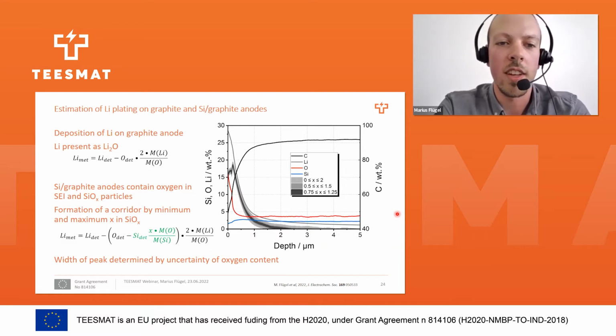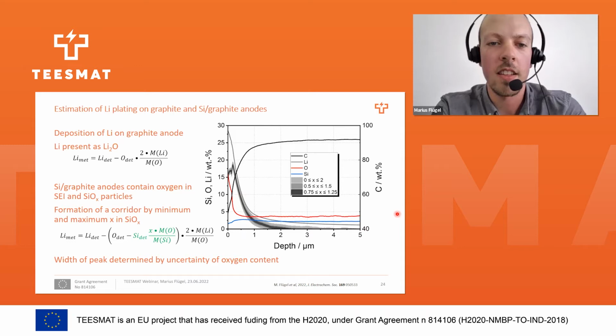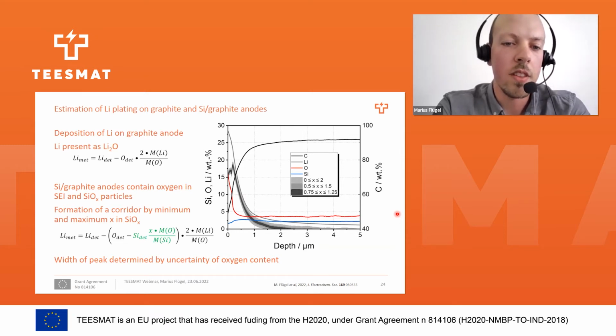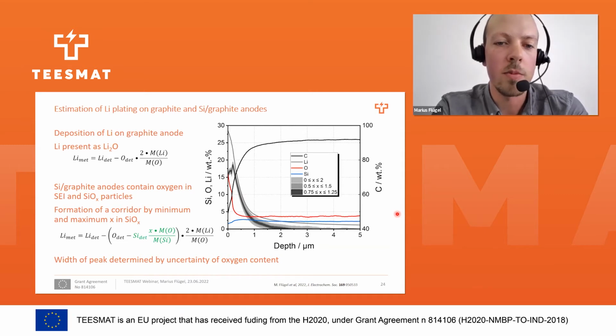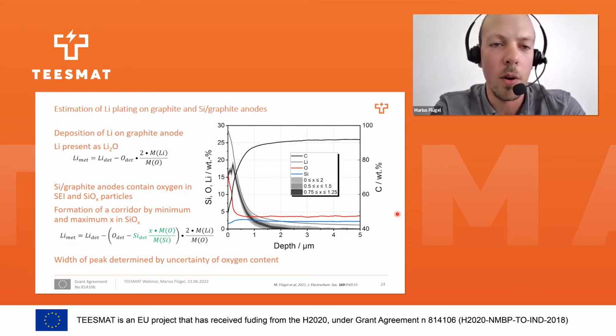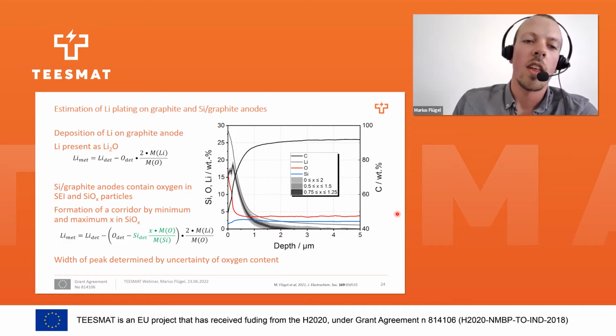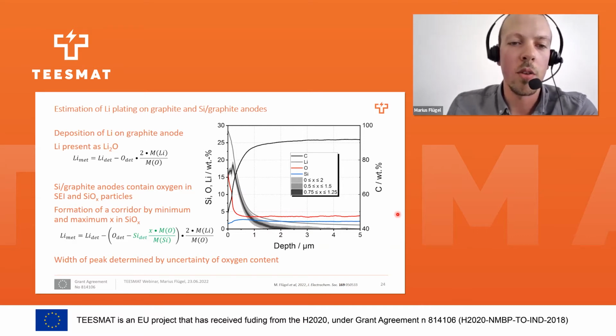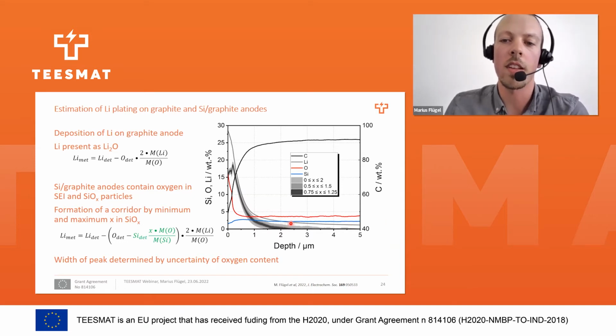For silicon-containing cells, this assumption is not so easy because silicon oxide also contains oxygen, and we have to subtract the amount of oxygen bound in silicon oxide before subtracting the amount of oxygen bound in lithium oxide. However, we do not know the exact amount of oxygen in silicon oxide, therefore we can only give a corridor in which the minimum amount of lithium plating is located.